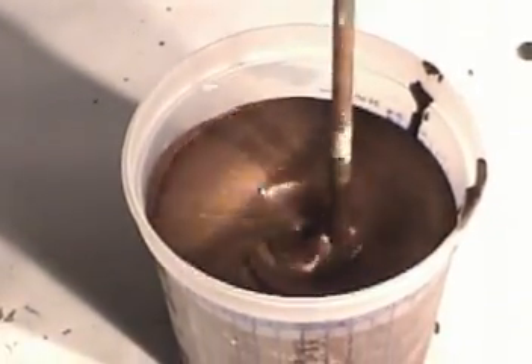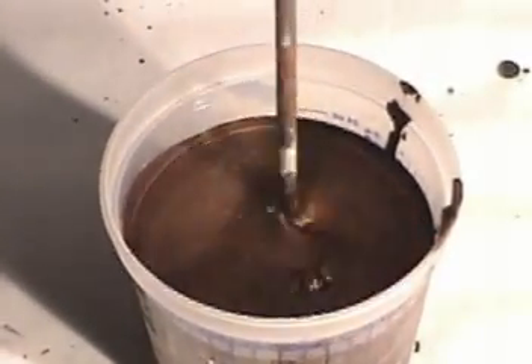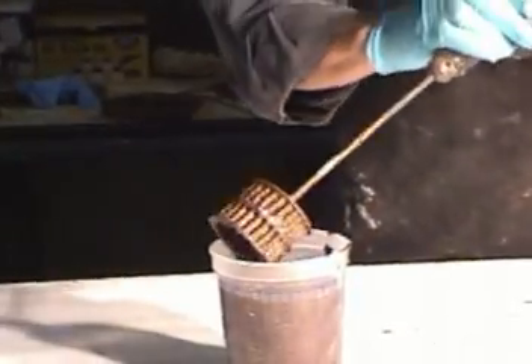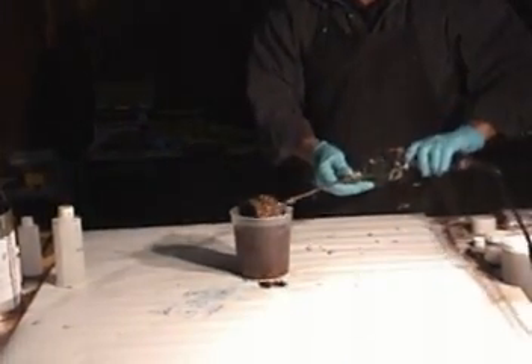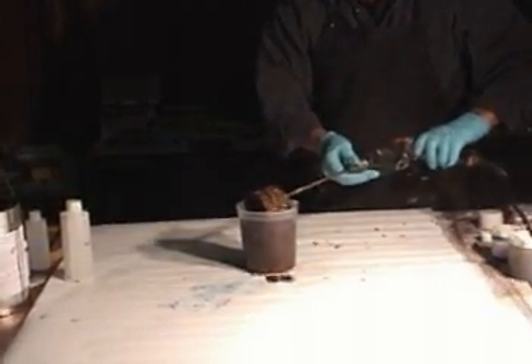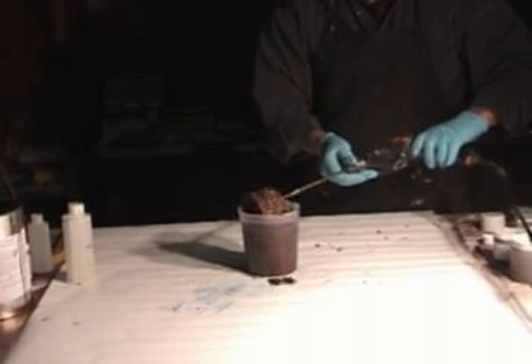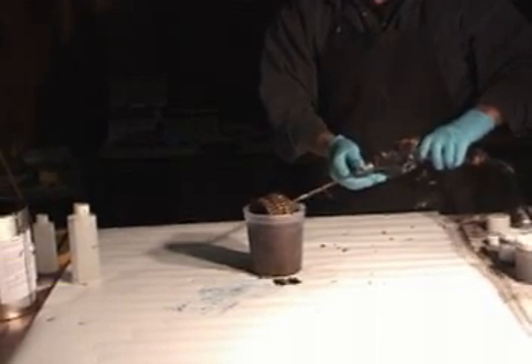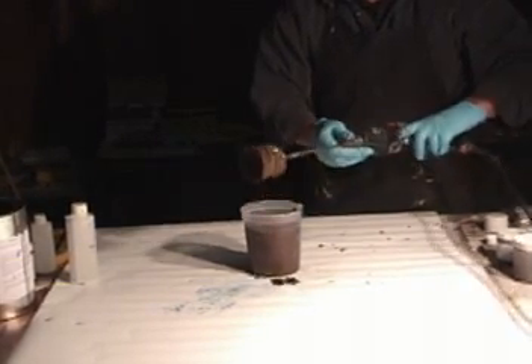And a quick note about temperature. If the components are too hot when you mix these together, it can actually start to cure quickly, almost instantly, and turn to cottage cheese. So it's very important to use the materials at 70 degrees so you can get the optimum amount of working time. Now our C coating is ready for application.